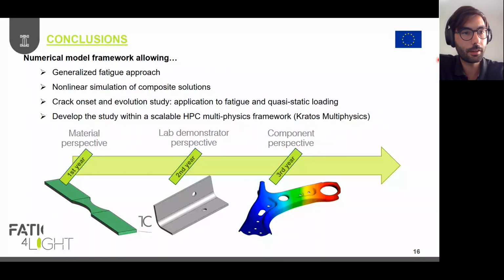Another cutting-edge characteristic of the methodology that we have been working on is that we are not only providing you the starting point of the fatigue degradation and the number of cycles in which it happens, but we can also see the evolution of the crack, because it can happen that the crack can start in one particular point, but the problematic zone or the crack development up to failure can be different. So we can capture this kind of behaviors.